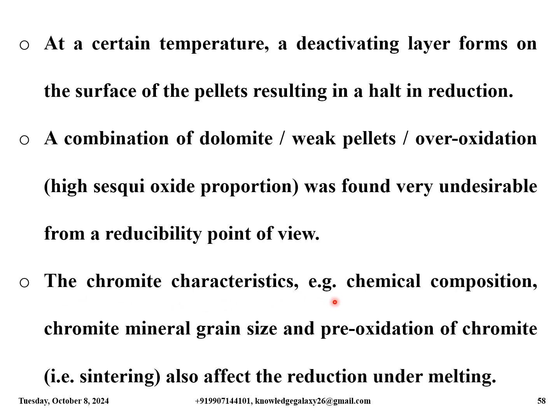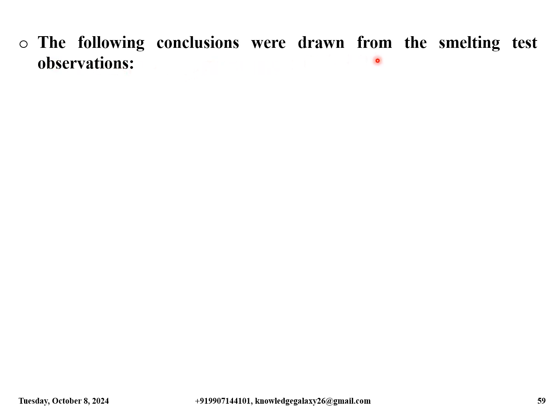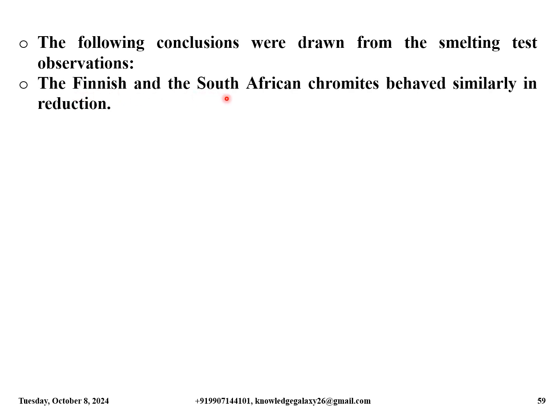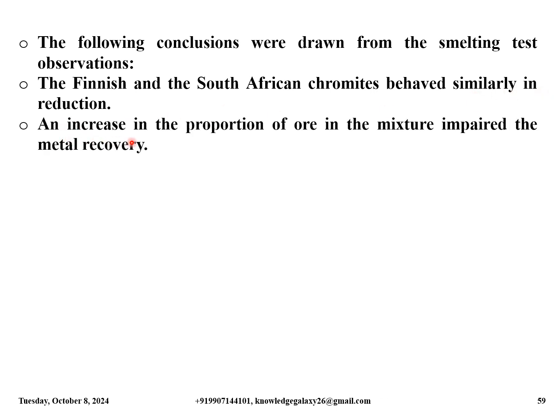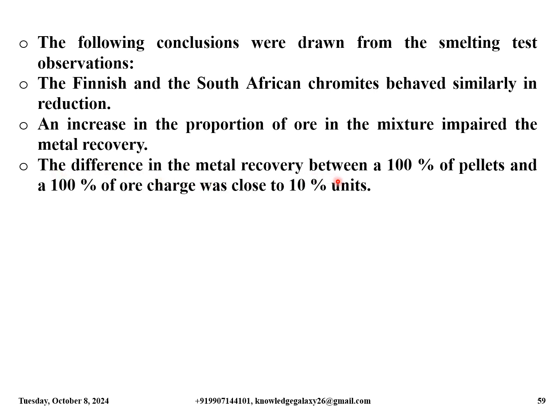The chromite characteristics, for example chemical composition, chromite mineral grain size and pre-oxidation of chromite, that is sintering, also affect the reduction under melting. The following conclusions were drawn from the smelting test observations. The Finnish and the South African chromites behave similarly in reduction. An increase in the proportion of ore in the mixture impaired the metal recovery. The difference in the metal recovery between a 100% pellet and a 100% ore charge was close to 10% units.